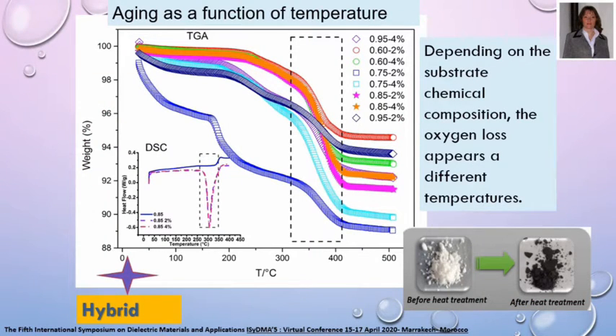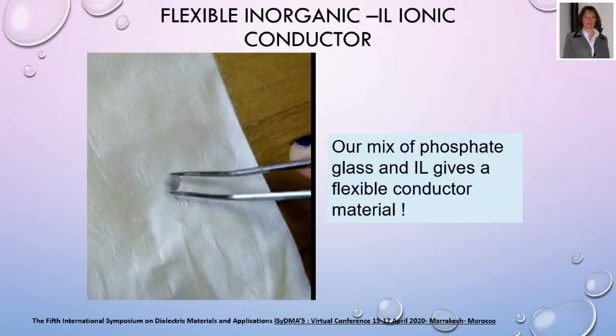We also show here that depending on the glass composition at the substrate, the hybrid conductor could resist up to 300 Celsius degrees before a degradation, before it loses oxygen. But the most outstanding result of this hybrid glass conductor is that with this material, we can obtain a flexible film, avoiding the use of a polymer.